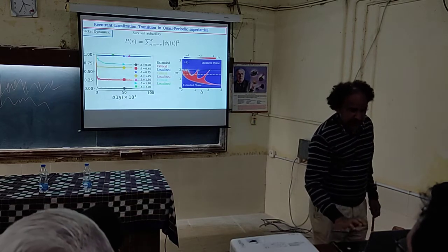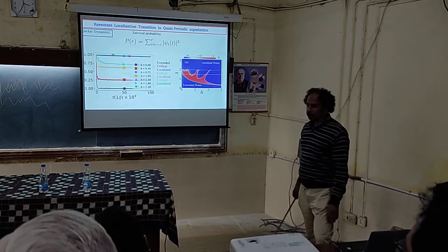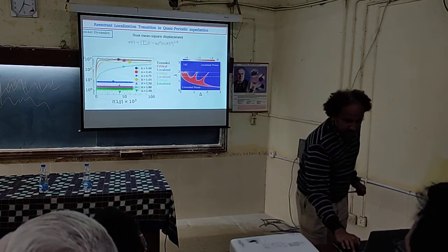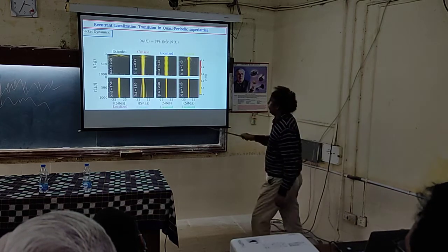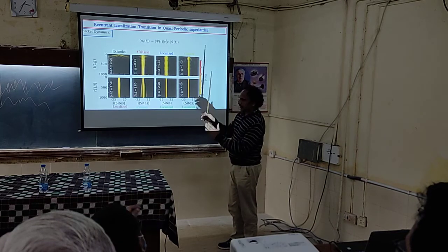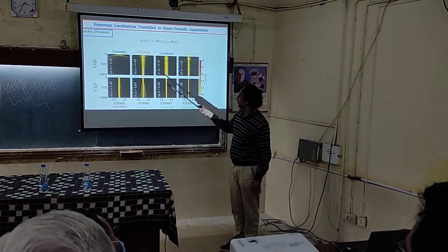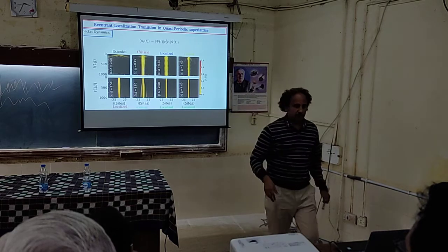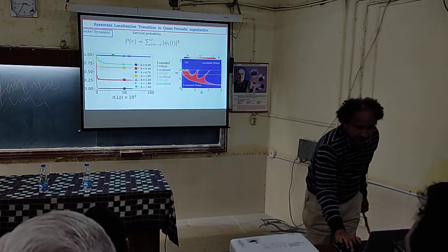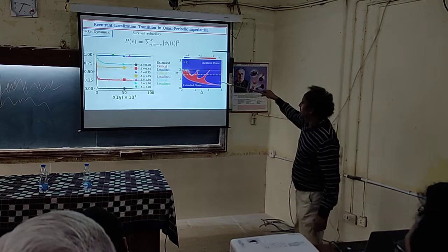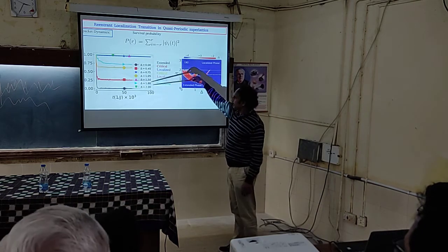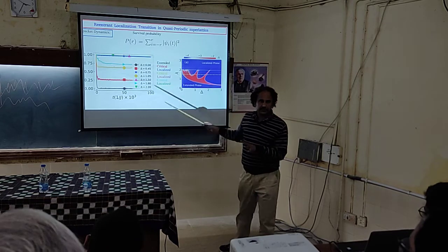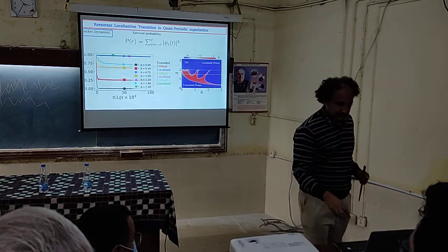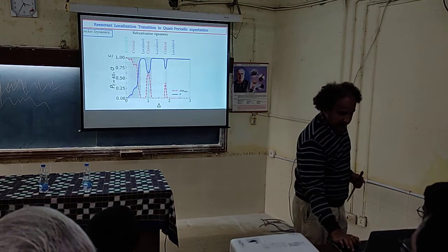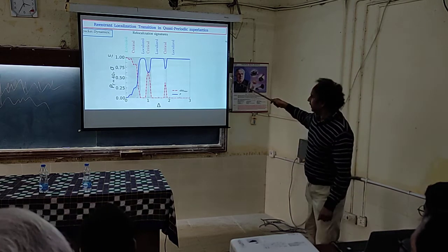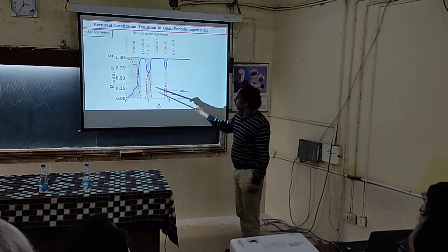Similarly, we compute the survival probability. Survival probability means the probability that the particle will remain somewhere near the center. So you take a range of lattice sites, 40 sites, and compute the probability. What is the probability of this particle staying near the center? This also shows a clear re-entrant signature here. So these can be experimentally accessed. I will skip this. And this is the phase diagram, where you can see the signatures in the experiment.